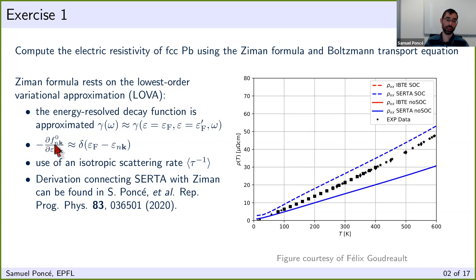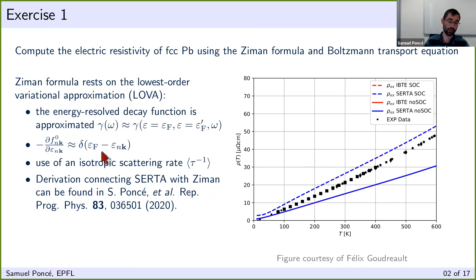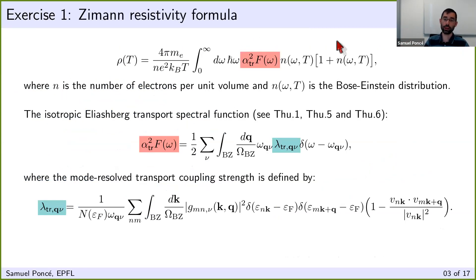You approximate the change of the Fermi-Dirac distribution function as a function of eigenenergies — this is in principle analytical because you can take the derivative and obtain 1/(k_B T) * f_0 * (1 - f). You can approximate this further, and you also need to use the fact that the scattering rate is isotropic. There is a derivation in a review paper showing clearly how to go from SERTA to LOVA.